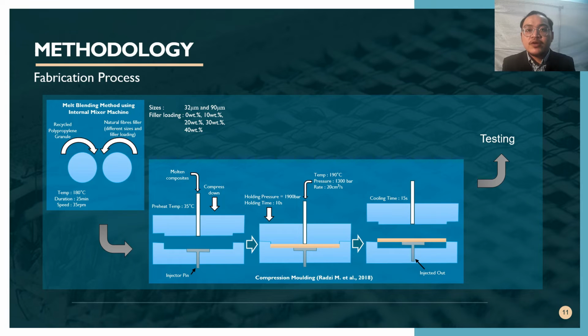Now, proceed with the fabrication process. Based on the previous study, RPP-KF and RPP-OPEFB composites of different compositions will be prepared by internal mixer at a temperature of 180 degrees Celsius, which is above the melting point of polypropylene. The mixture will be run for 25 minutes at a speed of 35 rpm. The composite will be integrated with reinforcement filler at 0 weight percent as control sample and 10, 20, 30 and 40 weight percent respectively. The size of the filler also varies, with 32 and 90 micrometer.